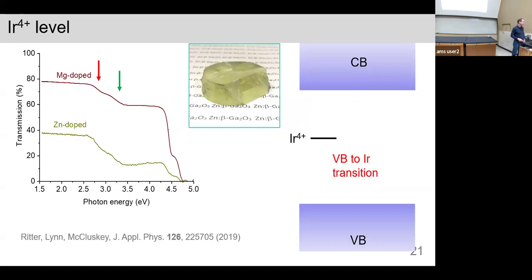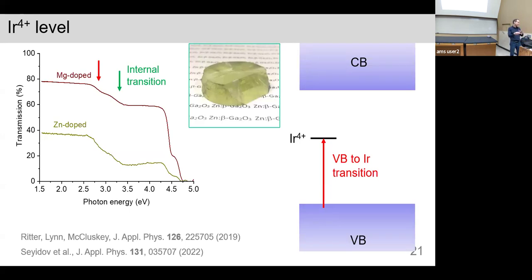So interestingly, with iridium itself, you can have a couple of electronic transitions. First is the valence band to iridium transition, and that is just an electron from the valence band going to the iridium level. And that results in this absorption threshold around 2.7 eV. You can also have what we think is an internal transition, just a D level to another D level, that gives this other bump in the absorption. So what you see is that you get a loss of transmission in the visible. So 2.7 is just getting to be about blue-green, and so it results in a yellowish color.